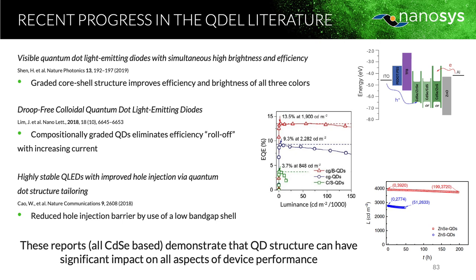Another one is droop-free colloidal quantum dot light-emitting diodes. This came from a group at Los Alamos. Typically, quantum dot devices have shown something people refer to as droop or roll-off in the efficiency versus luminance curve, which is here. The typical thing is that the maximum EQE is obtained at very low luminance, and then as you increase luminance, it falls off fast. What this group showed is that they could make quantum dots that had high EQE, and even up to over 100,000 nits, they're still maintaining that high efficiency. So I think this is also an important advancement.